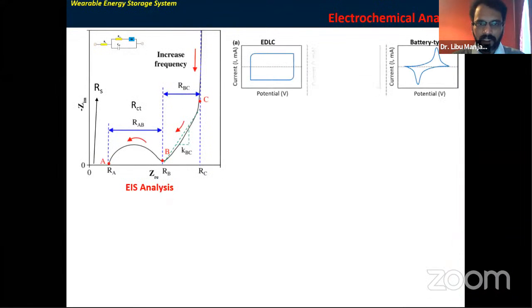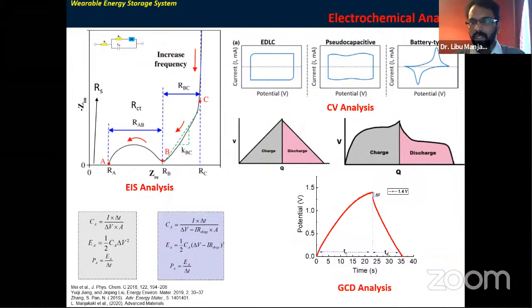And then this is some of the basic things. These are the three major characterizations we do for an electrochemical supercapacitor. The first figure is about EIS analysis, electrochemical impedance spectroscopic analysis. If your material is touching a solution, what is the resistance, and all these parameters you can monitor from the impedance spectroscopic analysis. And then there is EDLC for CV analysis. EDLC means electrochemical double layer capacitor, where we fabricate our supercapacitor using graphene or a conductive material. When there is no electrochemical reaction and you measure CV, cyclic voltammetric analysis, you observe a square shape. And if there is an electrochemical reaction, depending on the oxidation or reduction, you observe a pseudocapacitive material. This mainly depends on metal oxide or polymer-based devices. And for a battery type reaction, you can observe a strong redox reaction here.